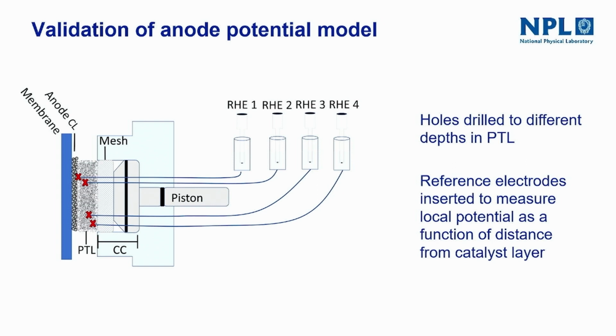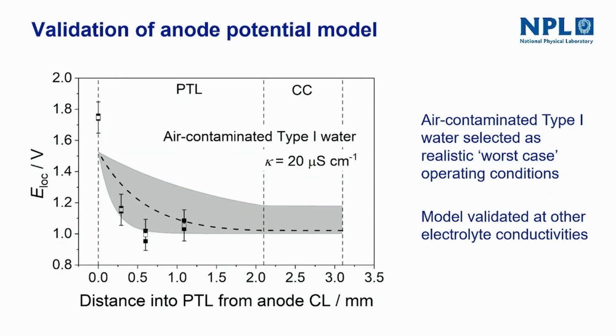We also experimentally validated the model using 4 different depths of reference electrode measurement in the porous transport layer, again using these external hydrogen reference electrodes. And the measurements did show that we could confirm this potential drop over the distance of a few hundred microns into the porous transport layer. So again, the first time anyone has shown this either theoretically or experimentally. And it's a very simple idea. Anyone who came to this with any kind of knowledge of corrosion would have had this same idea. But it's just bringing those two communities together.